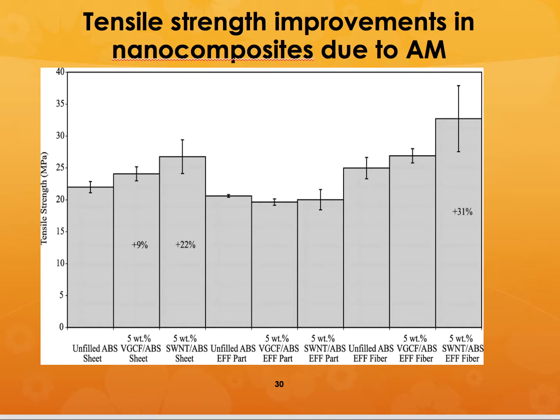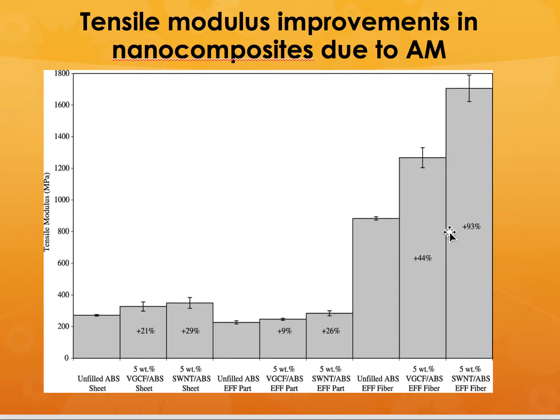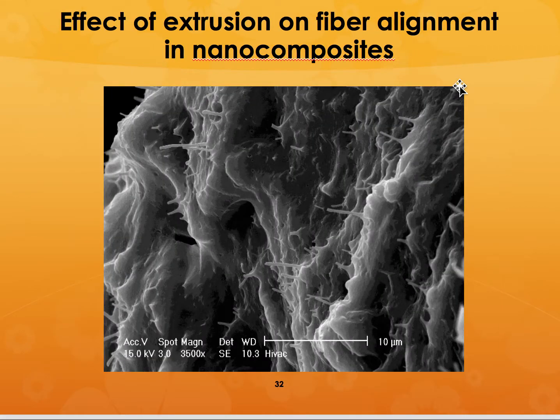So this shows you a bar chart of the different materials. ABS is acrylonitrile butadiene styrene, which is a standard engineering thermoplastic polymer that is used a lot in Stratasys type of equipment. So if it is unfilled, these are the properties, and this is tensile strength, and just 5 wt.% single wall nanotubes using the extrusion freeform fabrication improved the tensile strength by 31%. But the modulus increased by 93%. So, as I said to you, it is not that significant when compared to the vapor grown carbon fibers.